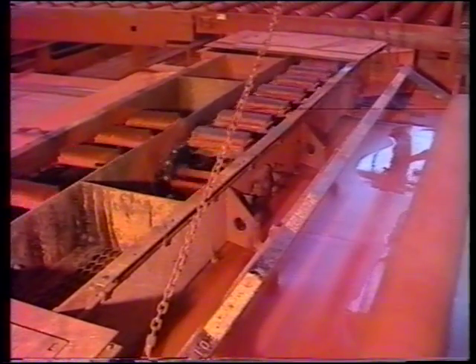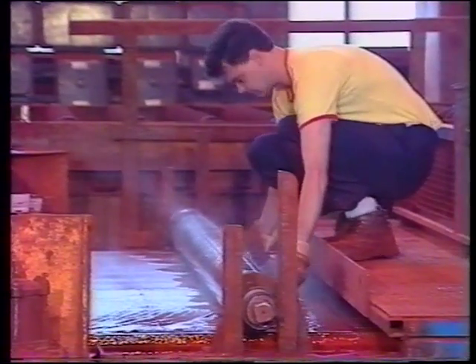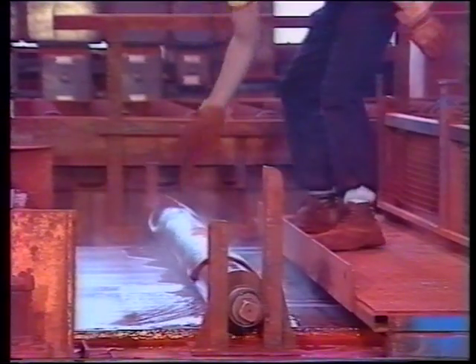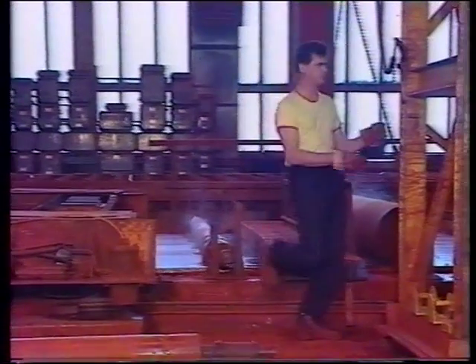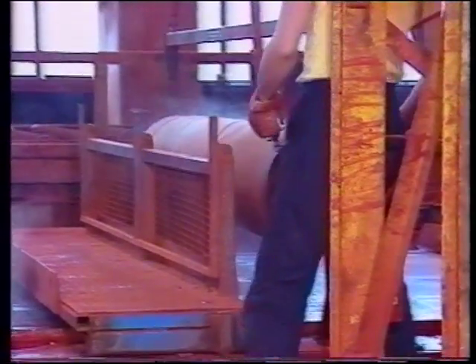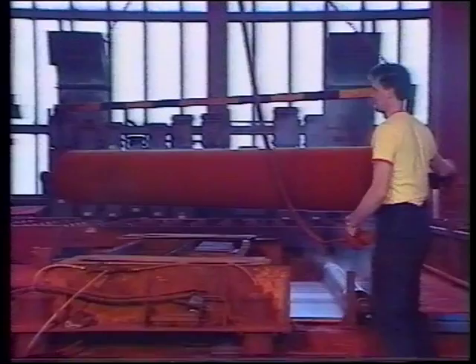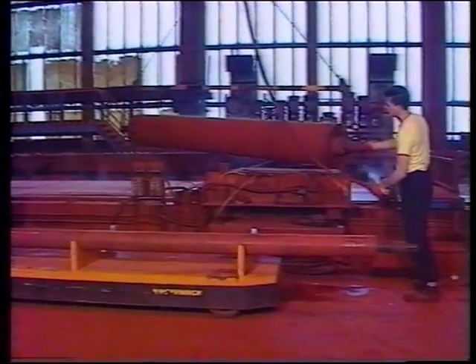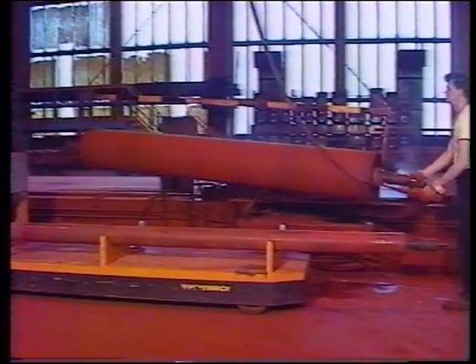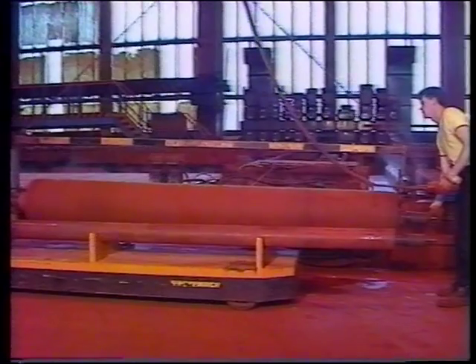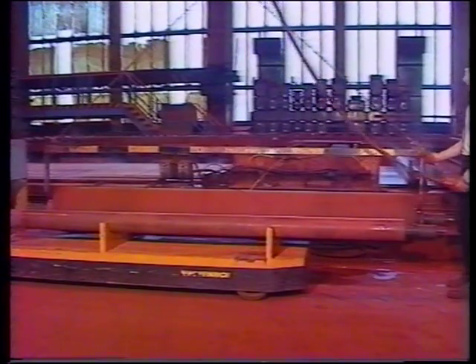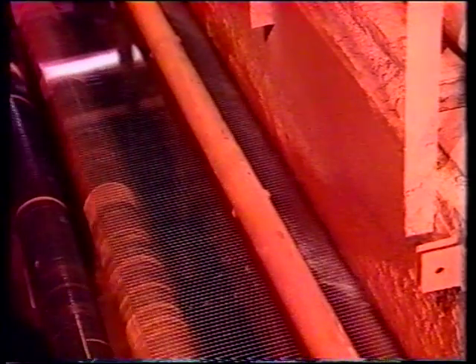A water spray in conjunction with a transverse brush system cleans the rouge and debris from the cloths, which are then rolled up and returned back to the start of the line. The glass is now washed and dried with an air knife and passed onto the warehouse examination booth.